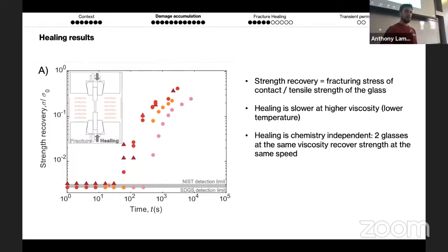It is chemistry independent. So triangles are one type of glass, and then the red dots are the same condition for the other glass. So same viscosity, but for the other glass. And what we see is that they recover strength at the same rate. So it might mean that, at least for these 2 standard glasses, healing is chemistry independent. And importantly, we see that the healing will start after a characteristic onset time. So for the triangle, it's about 15 seconds, 30 seconds. And for the orange, the characteristic time scale is going to be about here. Okay, so I've calculated those later.